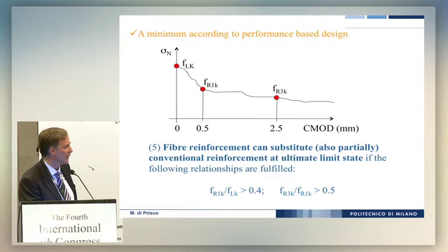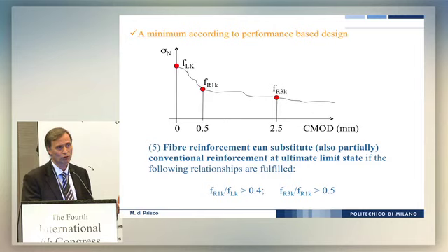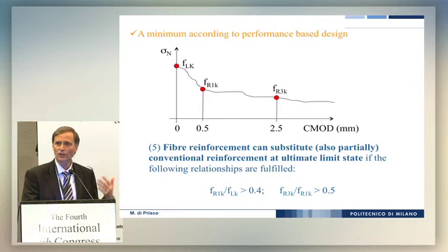And you need at least 40% to save at least 40% of your limit of proportionality as a serviceability limit state, and you need also another ratio of about 0.5 between the ultimate limit state and the serviceability in order to define it a structural fibre-reinforced concrete. Otherwise, you can profit of the benefit of this toughness, but you cannot enter in the definition of the constitutive laws, and so you cannot use as the ultimate limit state